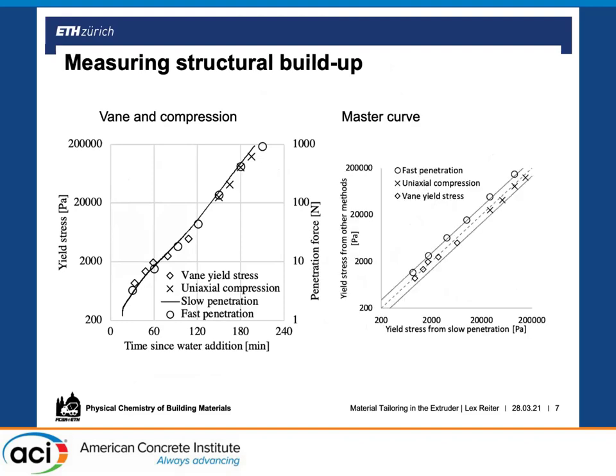Then we have also done a soil mechanical model that can directly and without any fitting relate what you have on the x-axis here, the yield stress from the slow penetration, to the other methods. So when I use yield stress evolution measurements, this is coming from this penetration test.